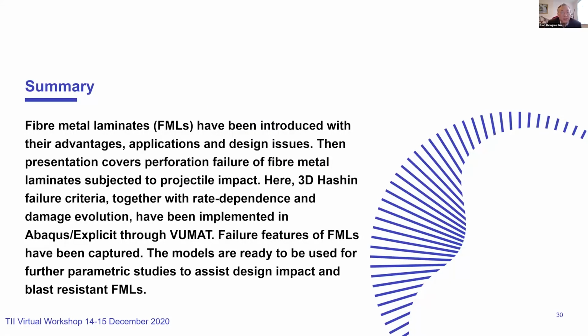Now I'm going to give a summary. Fiber metal laminates have been introduced with their advantages, applications and design issues. Then we covered perforation failure of fiber metal laminates subjected to projectile impact, as the tests show. And then 3D Hashin failure criteria together with rate dependency and damage evolution have been implemented in Abaqus Explicit through VUMAT. The failure features of fiber metal laminates have been captured for both impact and blast response. So the models developed are ready to be used for further parametric studies to assist the design of impact and blast resistant fiber metal laminates.